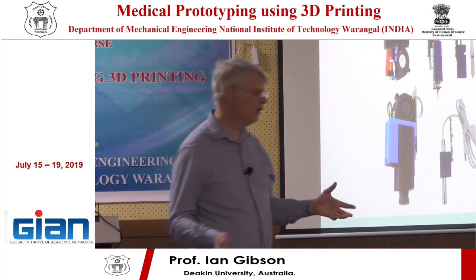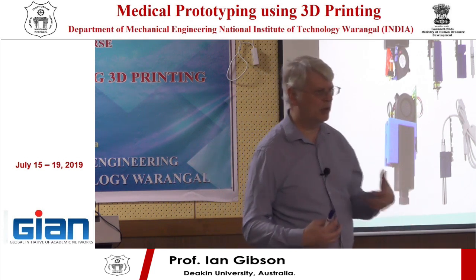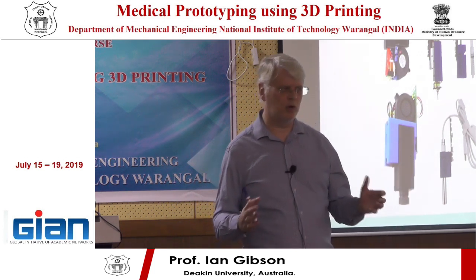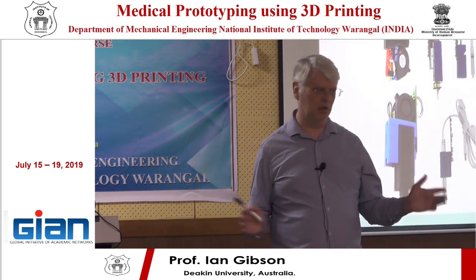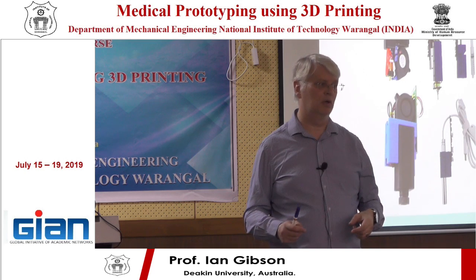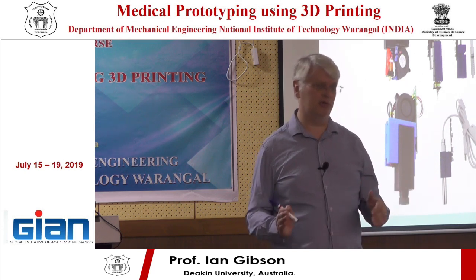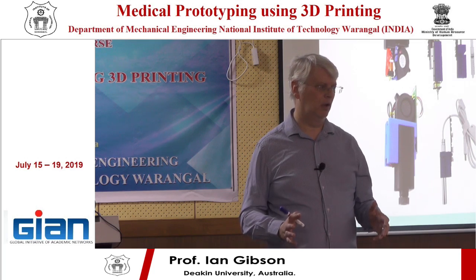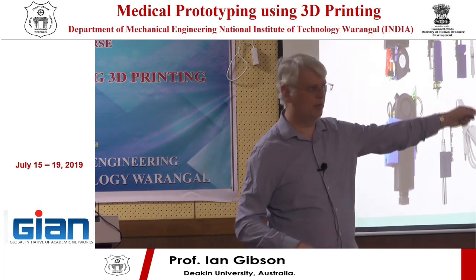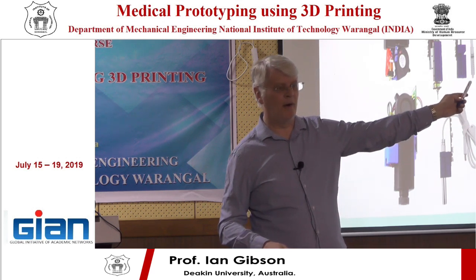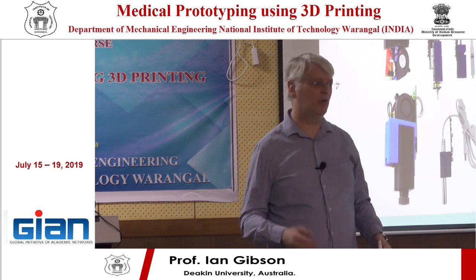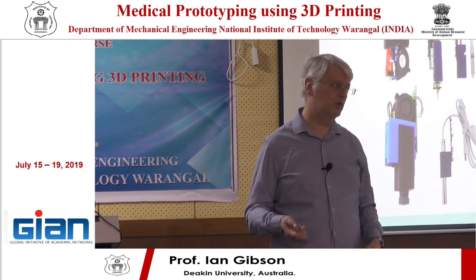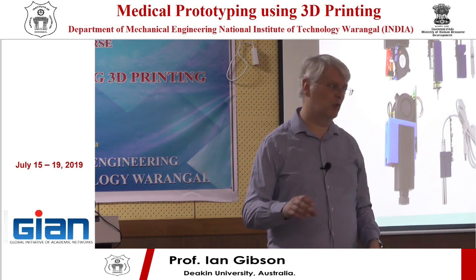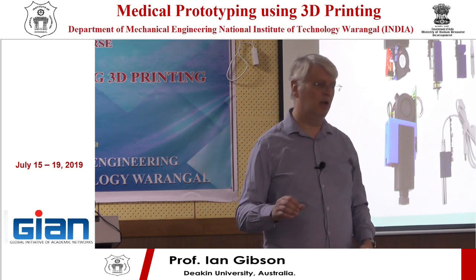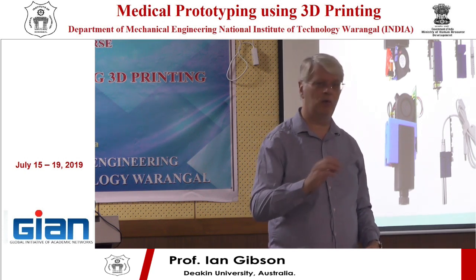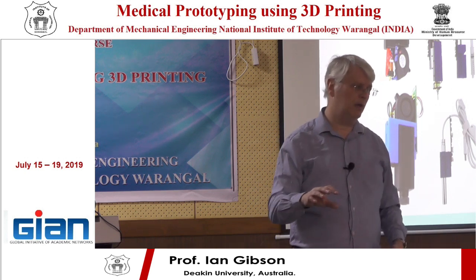One of the things that I learned from working with biochemists in the area of tissue engineering is that once I give them a scaffold, that's only the start of their work. They spend a load of time trimming the scaffolds, as I mentioned. Another thing is quite often you etch the scaffolds. You might immerse into a weak acid solution, and that gives you a surface texture, which then will allow your coatings to be applied.